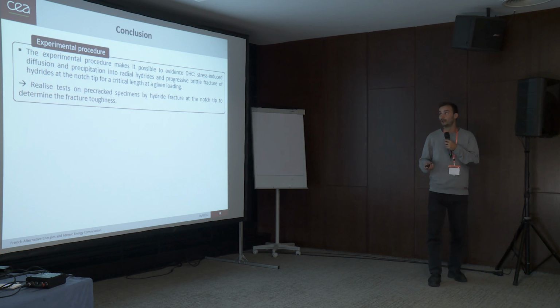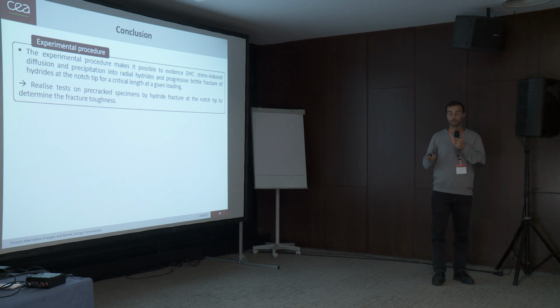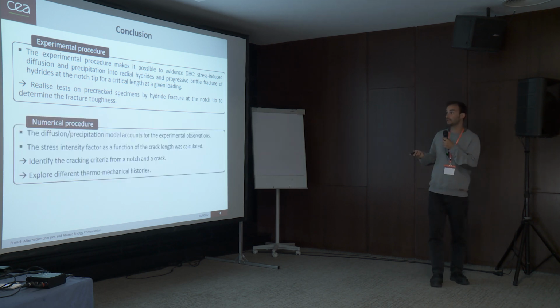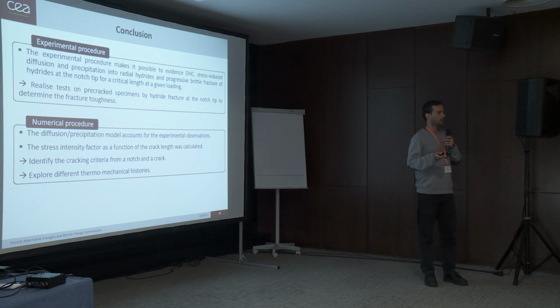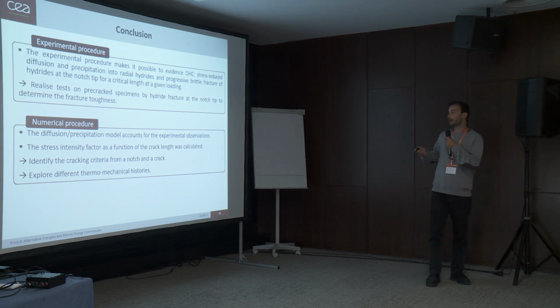So to conclude, we experimentally showed DHC, so the stress-induced hydrogen diffusion at the notch tip and its precipitation into hydride, its brittle fracture and crack propagation. So now we want to realize tests on pre-cracked specimens by fracture of a hydride at the notch tip to determine the fracture toughness. And numerically speaking, we implemented a diffusion precipitation model, and this model accounts for the experimental observation, and the stress intensity factor was calculated as a function of the crack length.